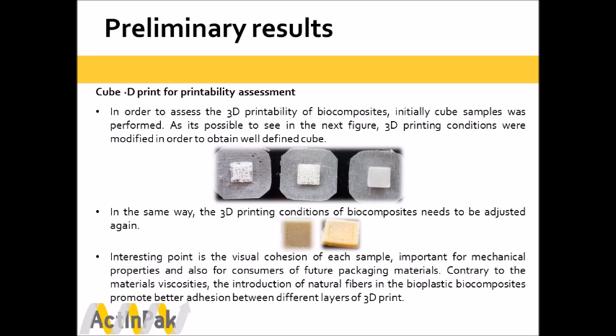As it's possible to see, 3D printing conditions were modified in order to obtain well-defined cubes. An interesting point is the visual cohesion of each sample, important for mechanical properties and also for consumers of future packaging materials. Contrary to the materials' viscosities, the introduction of natural fibers in the bioplastic biocomposites promotes better adhesion between different layers of 3D printing.